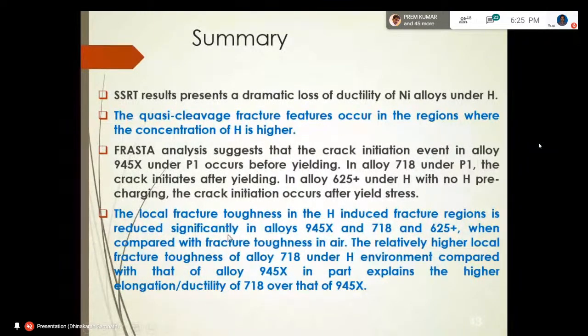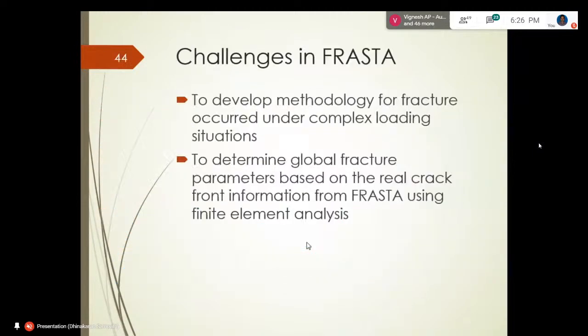So what this tells us is, of course the SSRT shows loss of ductility, but there are some gaps which we need to address. Fracture surface topography analysis is helpful to do some postmortem analysis. It's a technique that can be used for fracture replay analysis using the topography of the fracture surfaces. And also we can see the local fracture toughness between different alloys. So that's a pretty useful thing to do. We can also understand the effect of microstructure locally. We can bring a correlation and understand the microstructural issues.